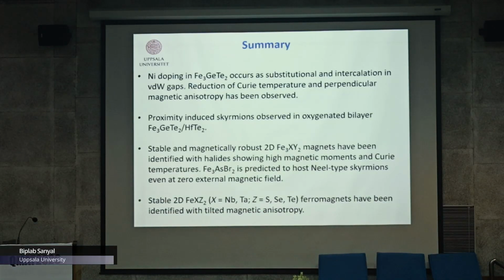So now I come to the conclusion. I have talked about iron germanium telluride, Fe3GeTe2, which is a centrosymmetric two-dimensional ferromagnet. But when you put nickel into it, some of the nickel atoms go to the substitutional sites, substituting iron. Some go to the van der Waals gaps, and then there is a certain combination by which you can actually decrease the exchange parameters and the perpendicular magnetic anisotropy. These people haven't looked into the spin glass physics yet, but I am also sure that something will happen in this material also. Then this was a prediction of proximity-induced skyrmions if you have a certain design with heterostructure.